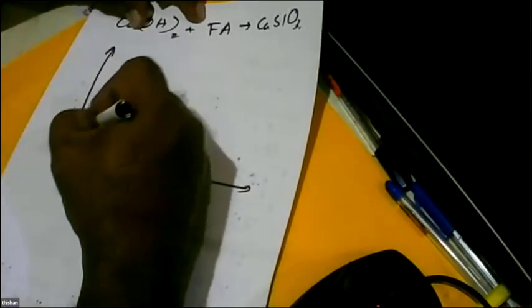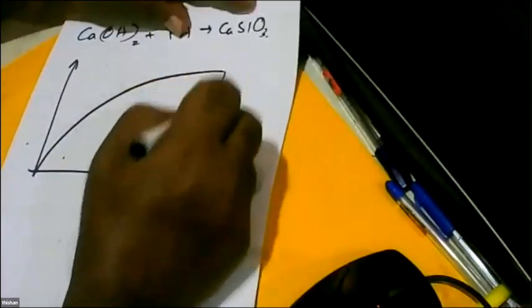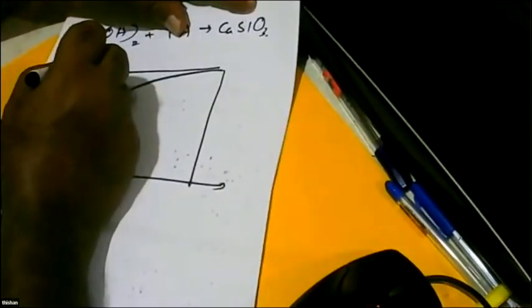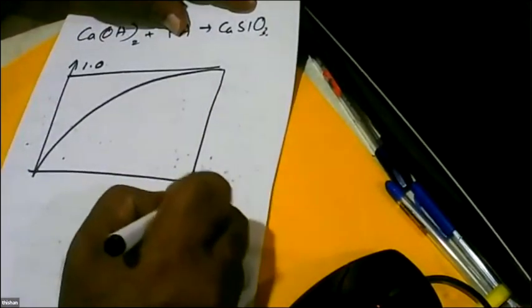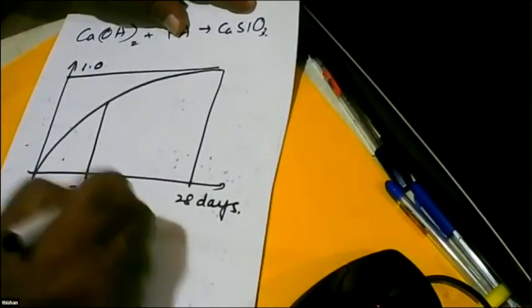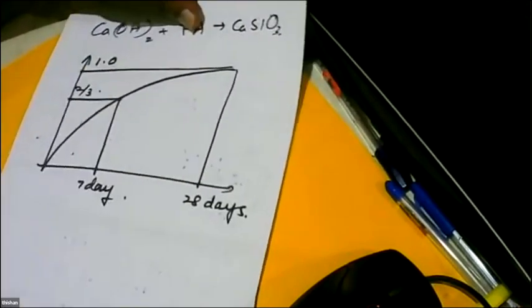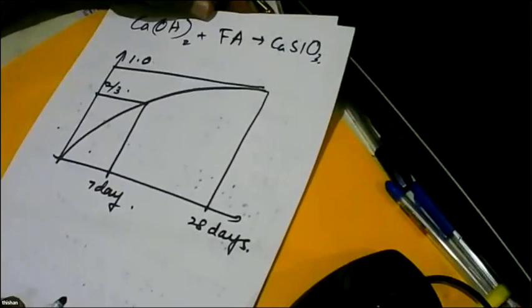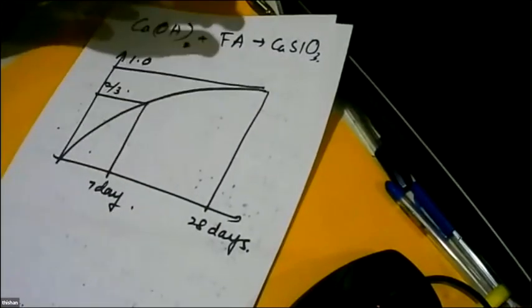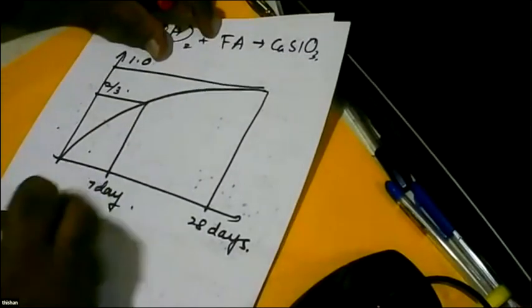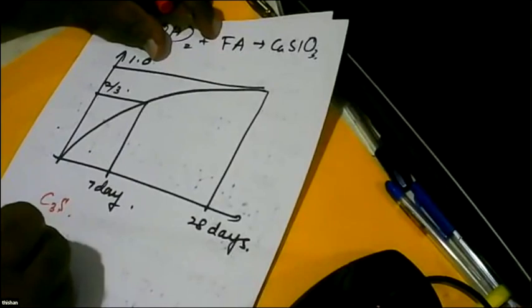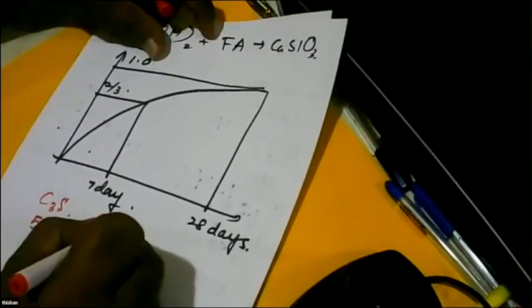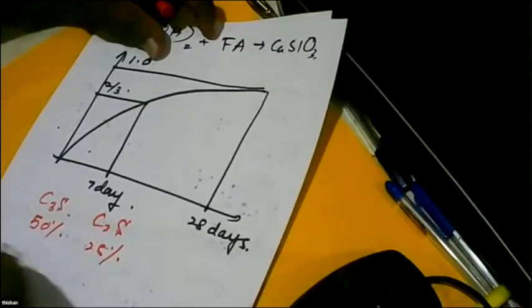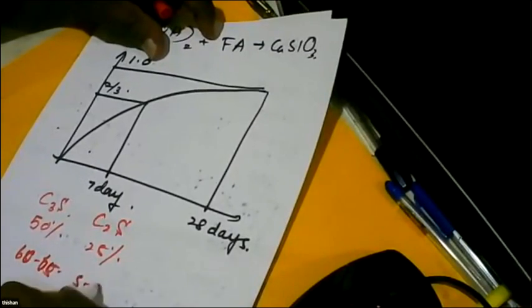Now if you look at the textbook, what the textbook says, if you are expecting the final 28 days strength as 1, in 7 days we get 2/3 of strength. We get 2/3 of strength, right? This is what the textbooks say. And the textbook curve was done when tricalcium silicate was limited to 50%, dicalcium silicate was 25%. Now today, what do you get? You get about 65 to 70% of this, 60 to 65% of this, only 5 to 10% of this.